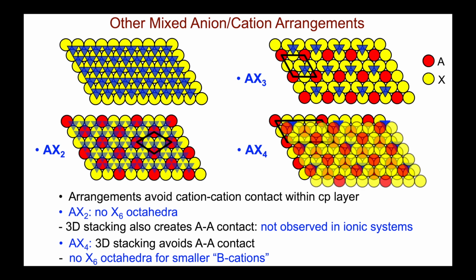However, when we put on the next close packed layer, if we make sure this next close packed layer avoids AA contacts, then you'll find that when I put that layer on top of the first, now those potential possible octahedral sites no longer have 6 anion neighbors. They had 3 below, but now we can see for this one there is a red, there's another cation.